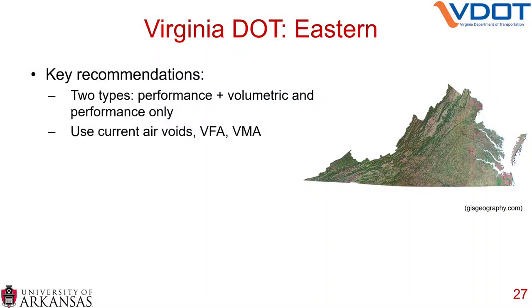Now, looking at the Virginia DOT, which is in the eastern part of the United States, they had some key recommendations. They used the two types that were defined in the NCAT report, performance plus volumetric and performance only. So they kind of used a hybrid type approach. They did not recommend changing any current air voids, VFA or VMA, but they did have liberal ranges on these that were a little bit unusual for traditional Superpave mix design. So I think that they're kind of using some in-place specs that some people would consider improvements on traditional specs, but they had already made those improvements.